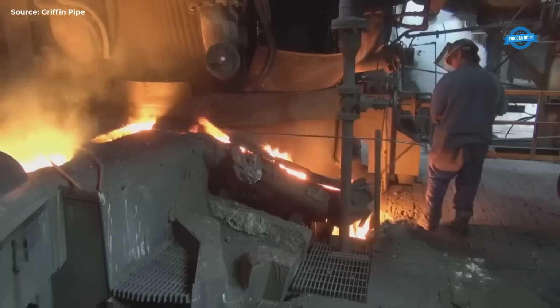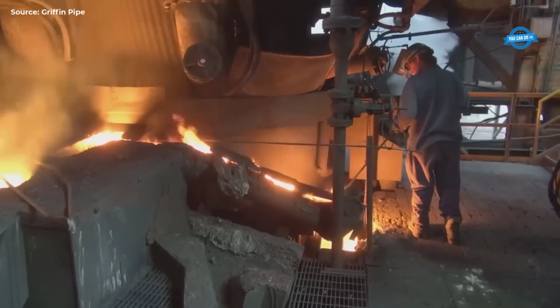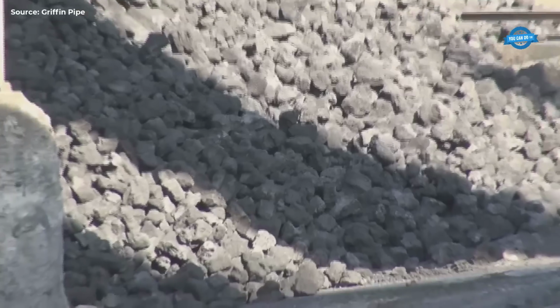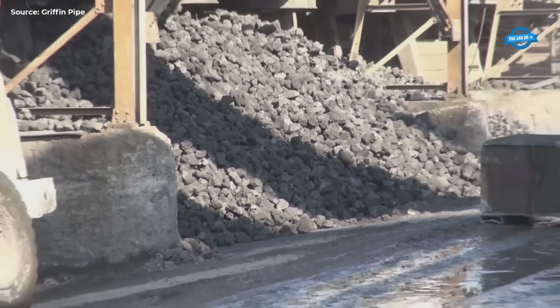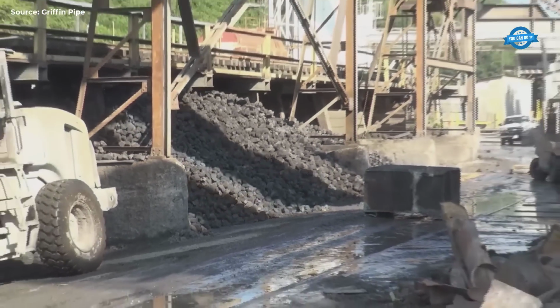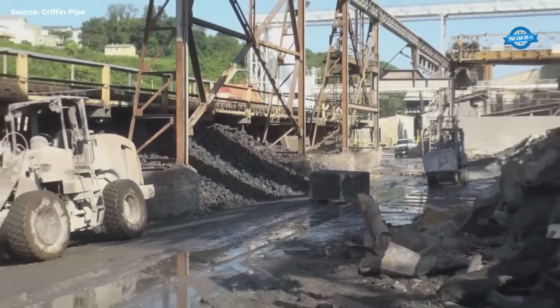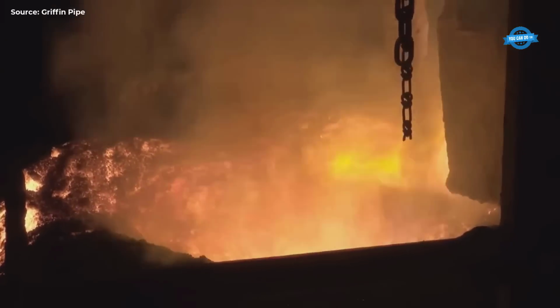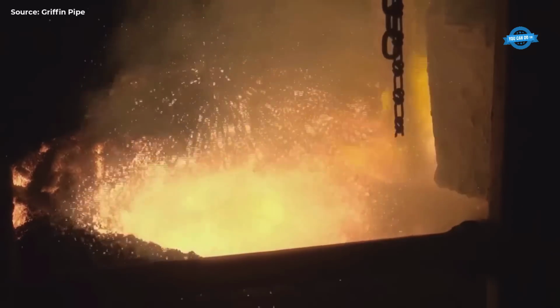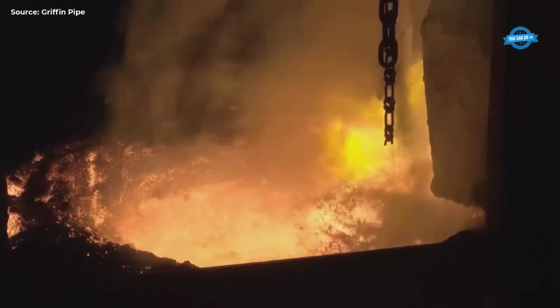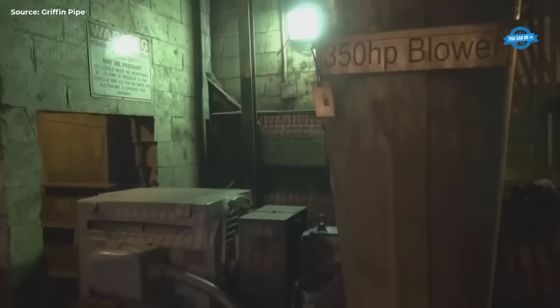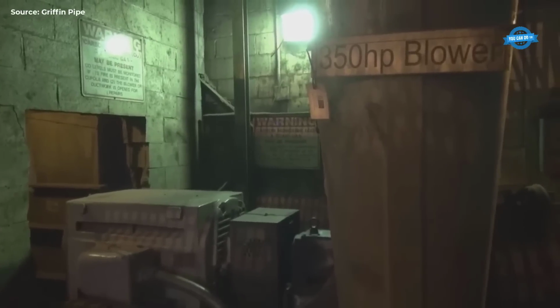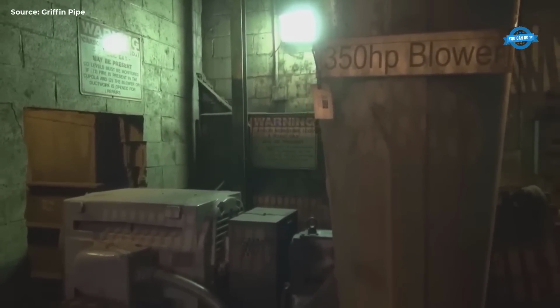We begin with raw materials, mainly scrap metal, primarily from shredded automobile bodies. The scrap is melted in a tall cylindrical furnace called a cupola, which uses coke as a fuel source and small amounts of limestone to help remove slag from the liquid iron. Preheated air is continuously blown into the coke bed at the base of the cupola to generate the high temperatures needed to melt the steel scrap.